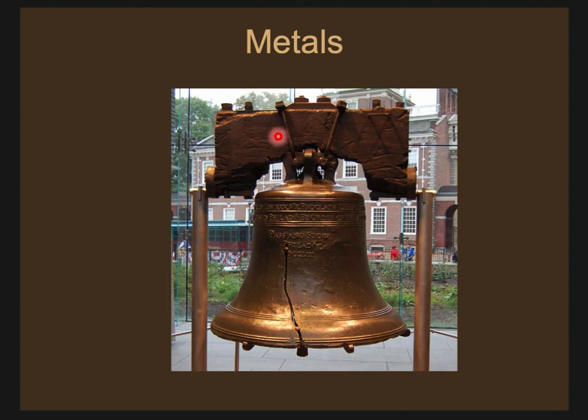That is, they didn't have a crucible large enough to cast the Liberty Bell, or to recast it, in one go, right? It had to be done in stages, pouring in one crucible, then another crucible. And those different batches of bronze were slightly different chemically from each other. So we can tell a little bit about the Liberty Bell from scientific analysis.